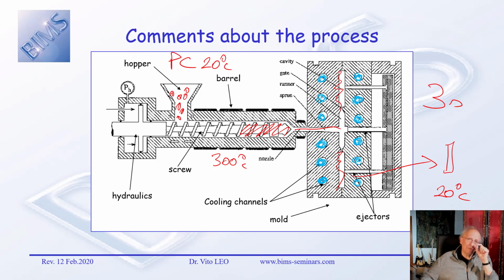And we have to do it fast, because if we go slow, the material will freeze before we reach the end of the flow, before we can actually fill the cavity. So it's fundamentally a bit of a crazy approach that is forcing us to go very fast. Now, to go fast, we need a lot of pressure. Plus, we tend to use this process only for very thin parts. What do I mean by very thin? Well, from 0.5 millimeter to a couple of millimeters, sometimes 3 or 4. But you don't want to mold a 10 millimeter thick part.